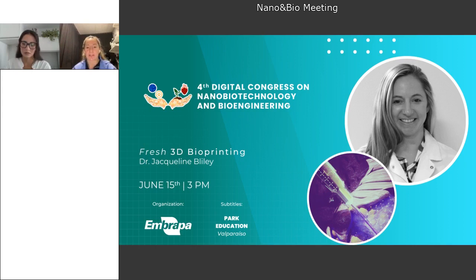And the other challenge is making sure that it actually functions like it should. So with certain acellular parts, like for example a valve, we do cyclic valve testing to see, does it open reliably and close reliably under certain pressures? Also, when does it start to fail? These are all really important questions that we're working on, but it takes time to develop a large data set to be able to put this into patients.